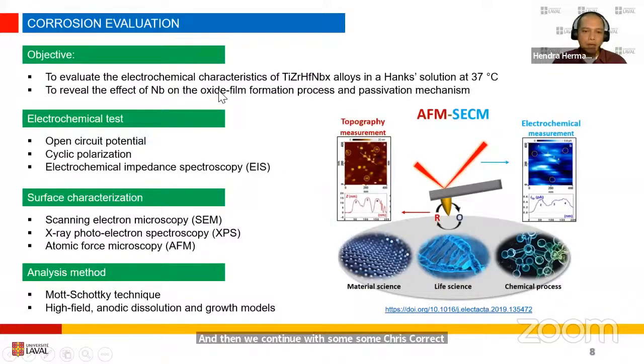And also, since we are dealing with a very thin film, in the order of 10 to 20 nanometers, we use X-ray photoelectron spectroscopy to characterize the chemical composition and also the phase or the compound found on the film. We also use atomic force microscope to study the dissolution during the corrosion test. And for the analysis, we use the Mott-Schottky technique and also the high field anodic dissolution and growth model. And as mentioned before, our main tool for this research was an atomic force microscope.